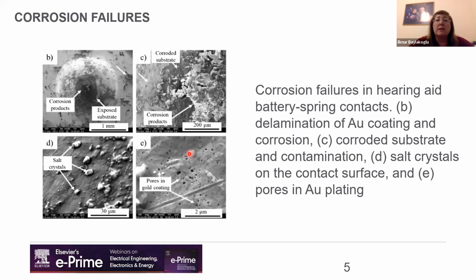Due to the pores, the galvanic corrosion occurred between the underlying nickel layer and the gold surface, and the resulting metal oxide had high brittleness and caused cracking or delamination of the gold surface, which made the nickel layer more exposed, as shown here.